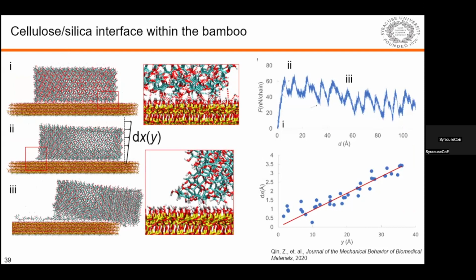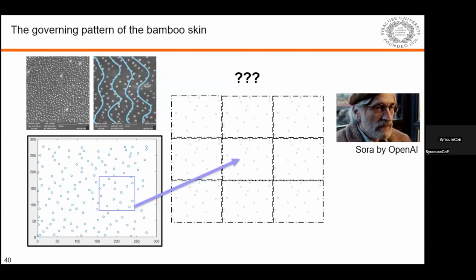We have atomistic simulations to study how cellulose interacts with the silica of bamboo. And we show that once you try to deform these cellulose, instead of failing at the interface, the cellulose will fail inside itself. That means the interface between the cellulose and the silica is very strong. But still, it doesn't explain why this conformation of the silica distribution contributes to the toughness of bamboo.